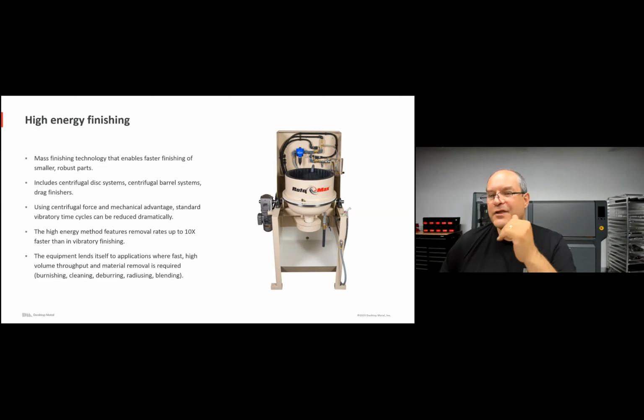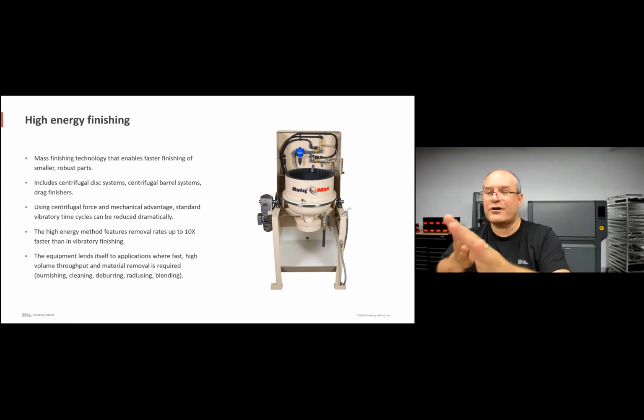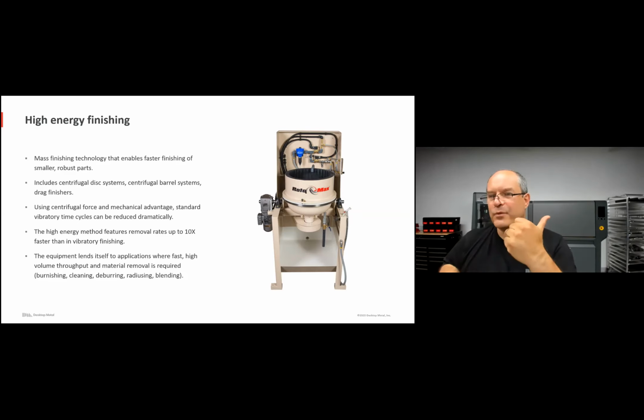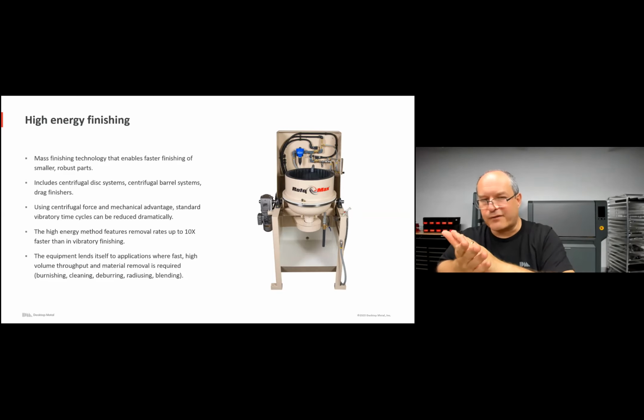Centrifugal barrel. The parts are getting spun much faster, and so the abrasive brushes past the parts at a much faster rate than with the vibratory bowls. And so as a result, your material removal rate can be 5, even 10 times faster. So that's dramatic. It really uses a lot of centrifugal force and this mechanical advantage to take away material.